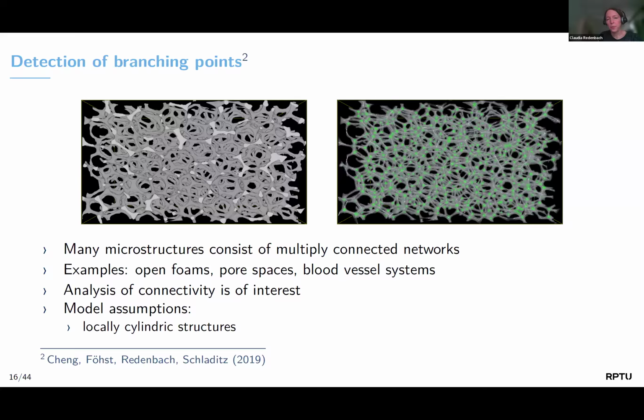And here we developed an algorithm for detecting such branching points, shown by the little green dots here, based on the assumption that you have something locally cylindrical, and at the branching points where the cylinders are stuck together, the structure is slightly thicker than in the center. So the idea was then we would compute a skeleton of the structure showing in white here, and we would look at local thickness maxima along this skeleton, and this way detect the branching points.